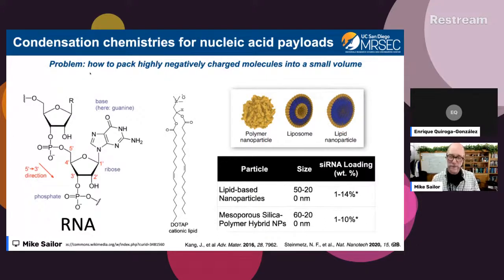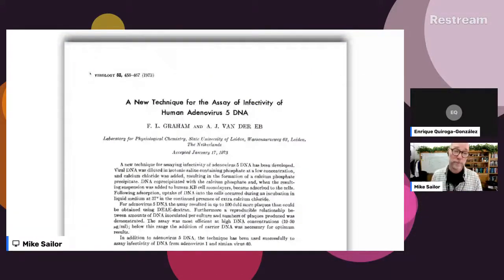The challenge was that with the current types of technologies, including COVID vaccines, it's really difficult to load this highly negatively charged RNA into a lipid. An example is shown in the table on the right, generally speaking, like a lipid-based nanoparticle or a liposome or these hybrid systems. We surveyed the literature about 4 or 5 years ago, and there was no nanoparticle that could load a nucleic acid, these highly negatively charged RNA or DNA therapeutics, to a level above about 15%. So that's one of the challenges. How do you get a lot of RNA into a small nanoparticle? Because of course you can get it to be more effective.